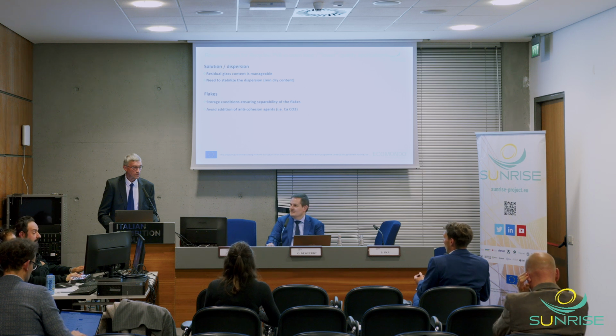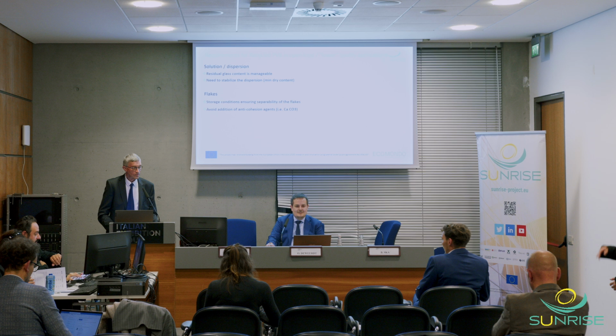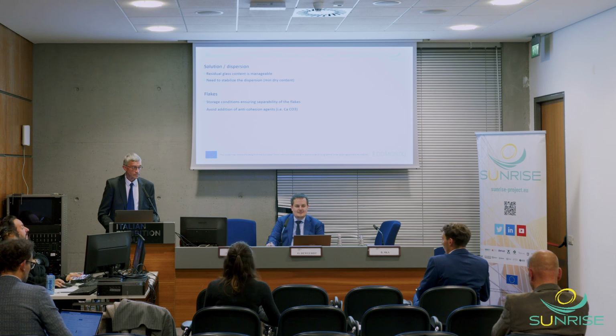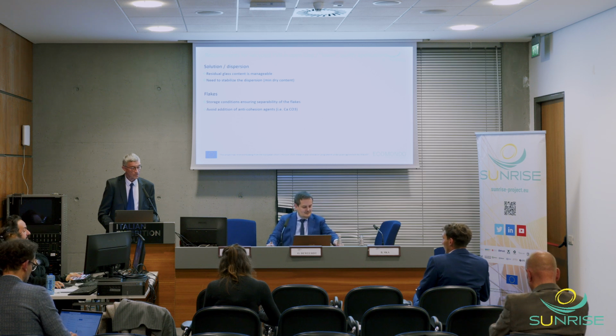But the glass has to be out of this material. Then it's no problem. When the glass is still inside of the PVB and it's getting chunky, then it's a lot of work. And basically the material is then lost. So the process has to be quite sharp to get the glass out. And then there are no problems with flakes or making a sticky mess.